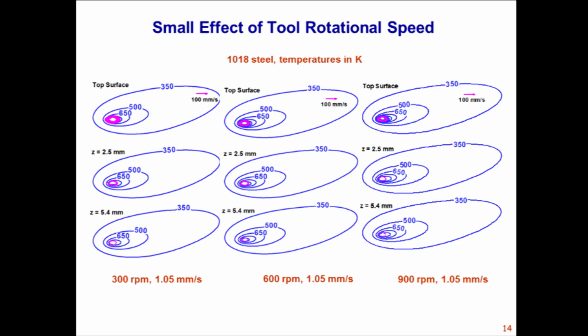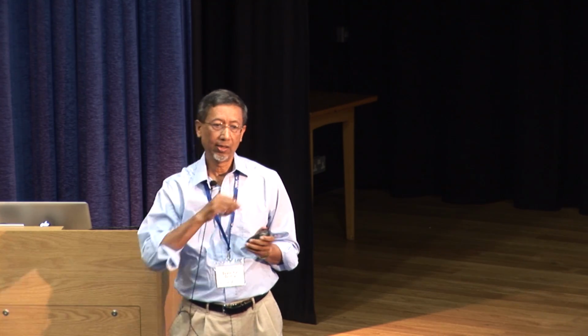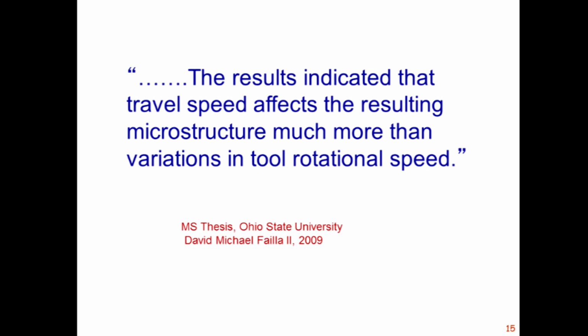In contrast, if you vary the RPM of the tool, the temperature fields do not change a great deal. They do change, but not something to write home about. So if you wanted a different structure, you actually have to vary the welding speed. That's your most potent variable. And it's validated by other people's independent work. Suresh Babu is in the audience. He was on the thesis committee of the student at Ohio State, our neighbor, and they found the same story. So this is not a surprise.